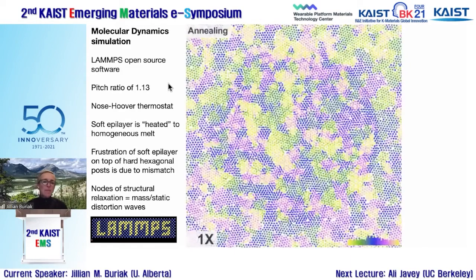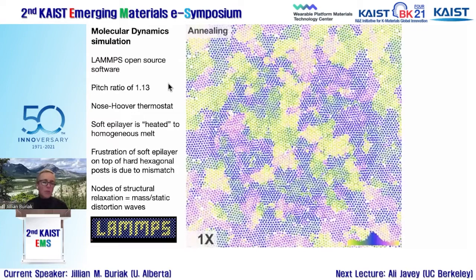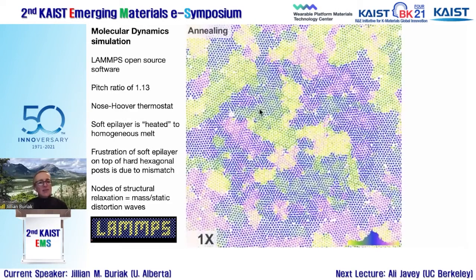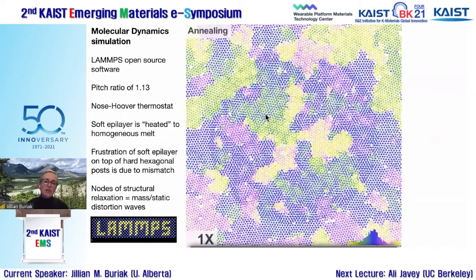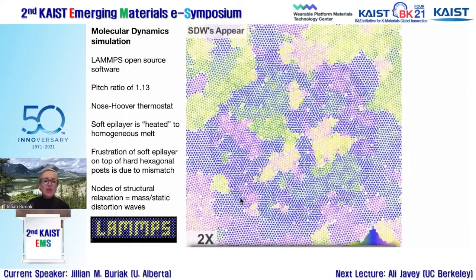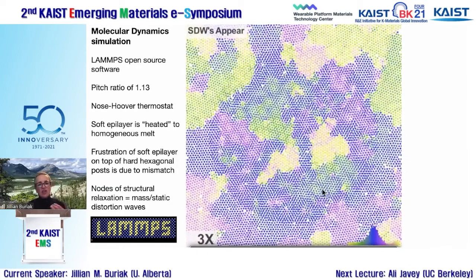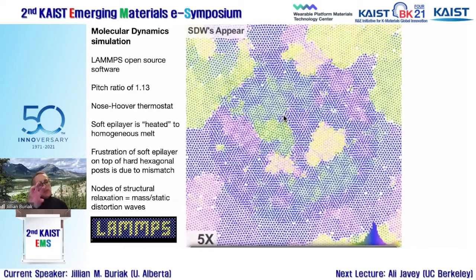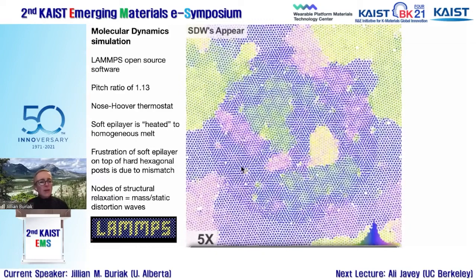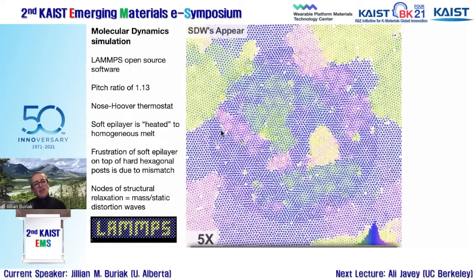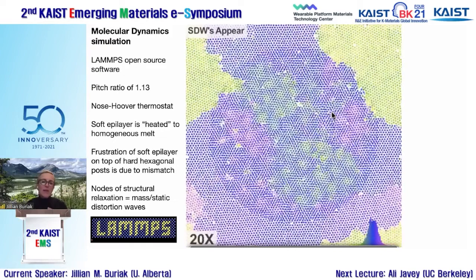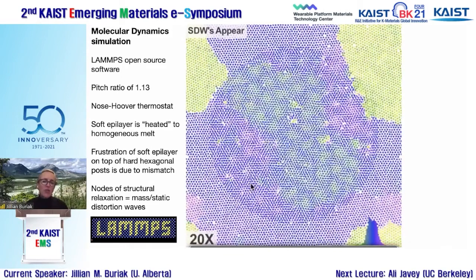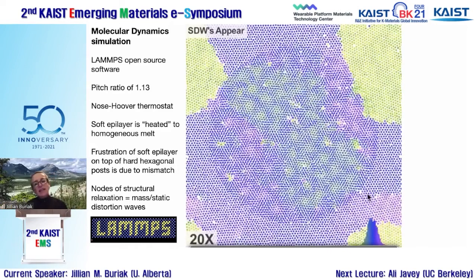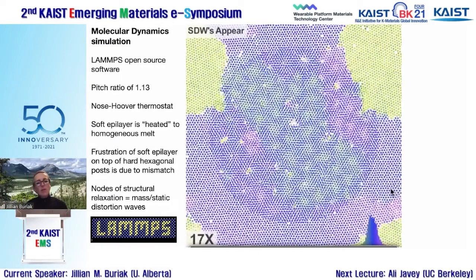So when we give the system time, and we give the system energy, so thermal energy, you start to see some of these triangular patterns that are typical of a Moiré superstructure. And we're going to speed this up because otherwise it's like watching paint dry. You can see the circle in the background that represents those hard dots. Again, we're going to speed this up, and you start to see those twists, those static distortion waves appearing. And so these are nodes of structural relaxation. So here we are, we've given the system energy. And you can see how they're actually grouped, kind of exactly what we saw experimentally. Down in the bottom right-hand corner is a histogram, and this histogram is telling us the angle of offset.